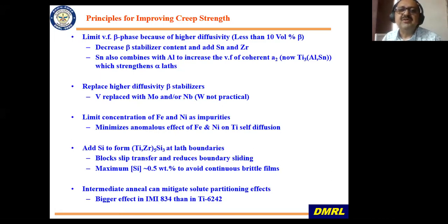So you decrease the amount of beta stabilizers and add neutral stabilizers like tin and zirconium. Tin is also combined with aluminium to precipitate alpha 2, which strengthens, and that is what is used in high temperature titanium alloys. And you replace the higher diffusivity beta stabilizer like vanadium with lesser diffusivity beta stabilizing elements like moly, niobium, etc., so that the diffusivity is lesser and you can get good high temperature properties.